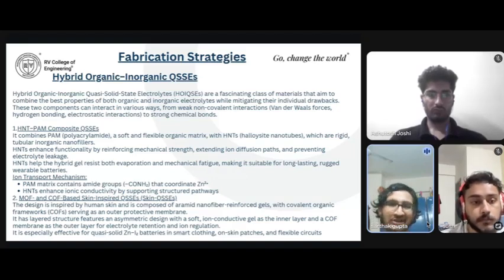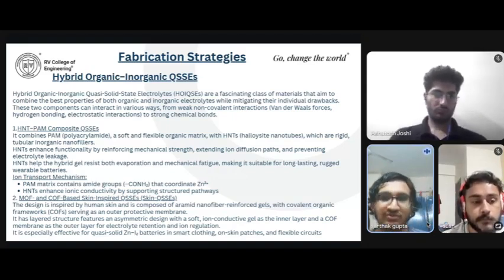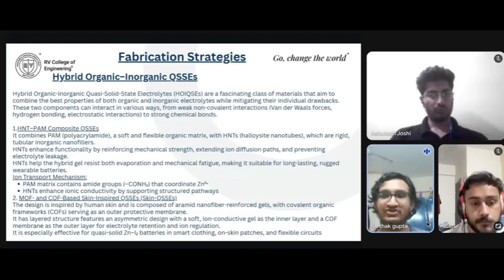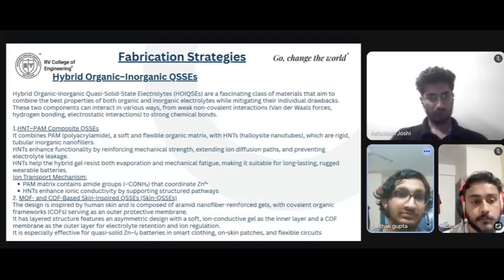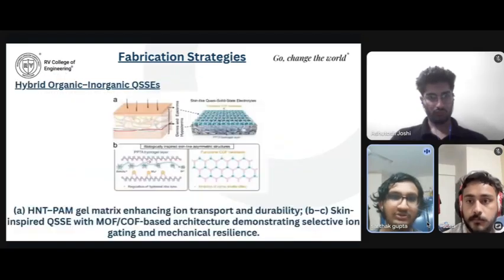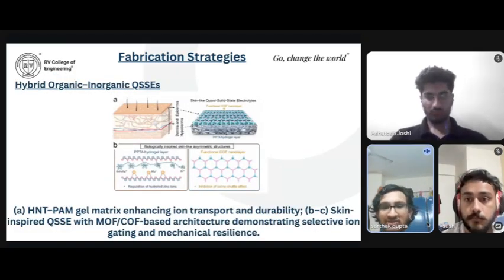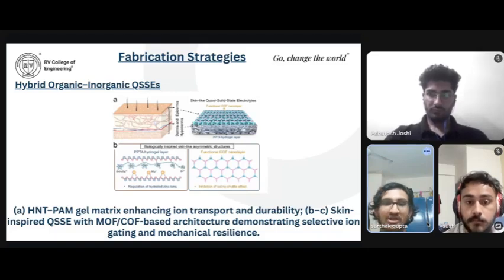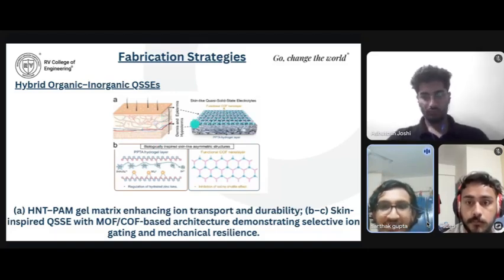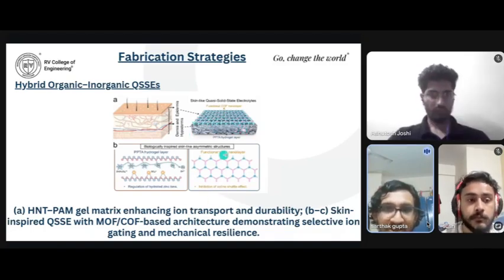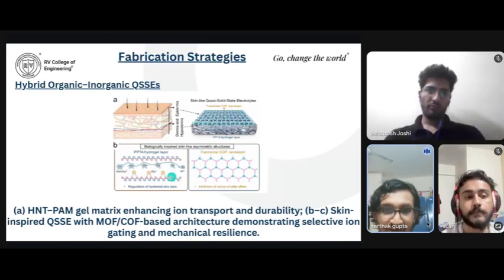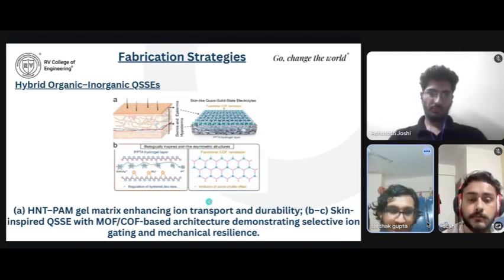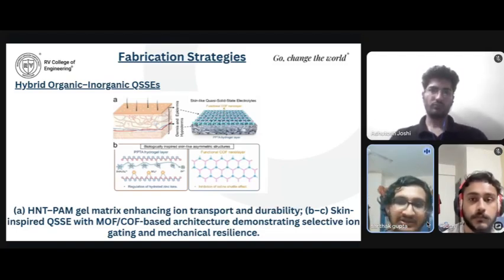The fabrication includes layering and cross-linking techniques to create an asymmetric structure. These electrolytes show promise for polysulfide blocking, moisture retention, and safe long-term wearable storage. So this is one example of how the HNT-PAM gel matrix enhances ion transport and durability. This is how the skin looks, and this is how they are trying to frame it: one hydrogel layer, then one layer above it. So this is a biologically inspired, skin-like asymmetric structure of a functional COF nanopolymer, with a MOF COF architecture demonstrating selective ion gating and mechanical resilience.